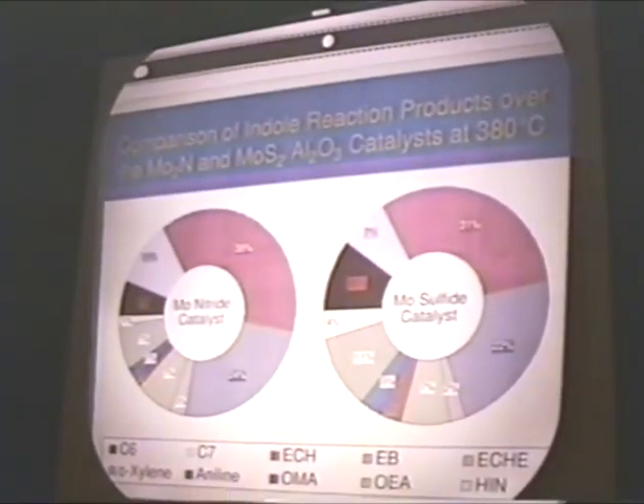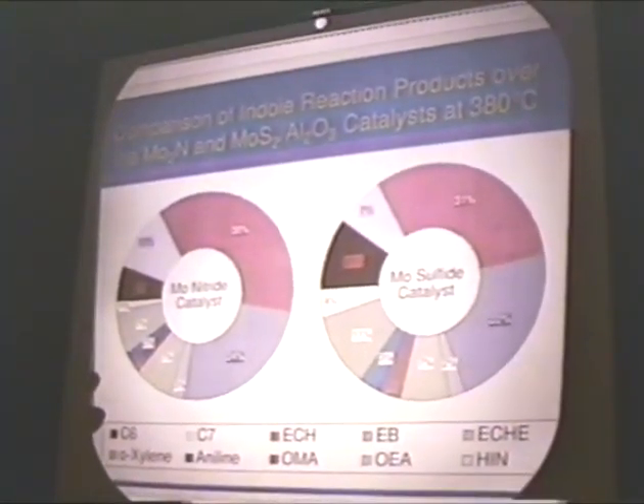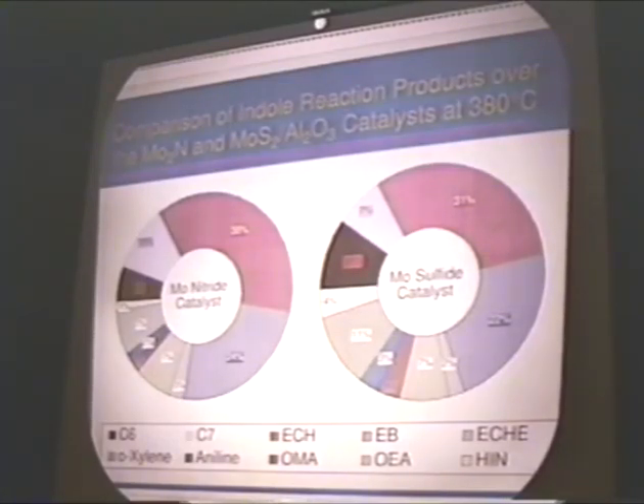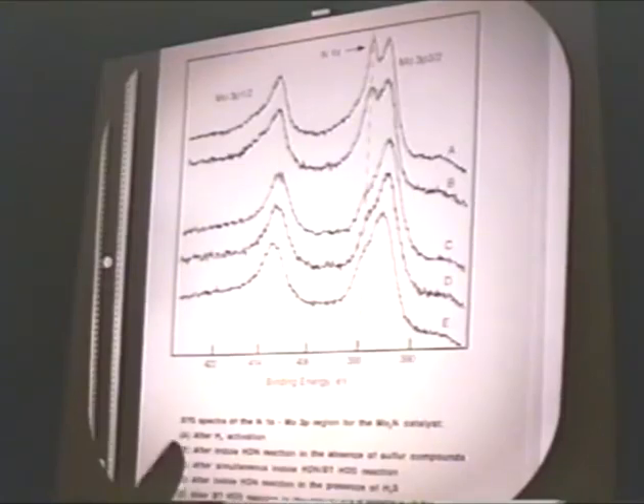Let's repeat the same comparison, this time at a higher temperature, 380 degrees centigrade. Again, the largest product that we obtain is ethyl cyclohexane over both catalysts, and as you can see, the product distributions are very, very similar. So now what has happened? The nitride catalyst, once we have some sulfur compounds present in the system, is beginning to behave very similar to a sulfided molybdenum catalyst. We wanted to see what kind of changes took place over the surface of these catalysts